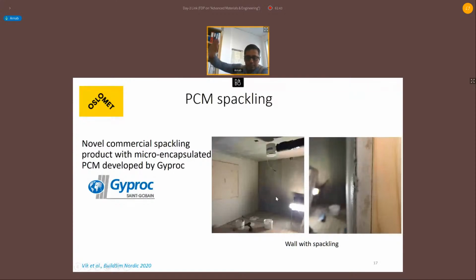But one important thing is that, as I mentioned, fire and flammability is an important thing. So one needs to apply a fire retardant white coating paint. So this is the gypsum board, which is linked with this wooden frame, and this is the phase change materials with near about 2 millimeter. It appears a bit thick here, but we measured in random sampling that it is in the range of 2 millimeter we applied.